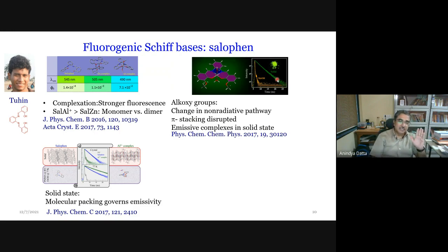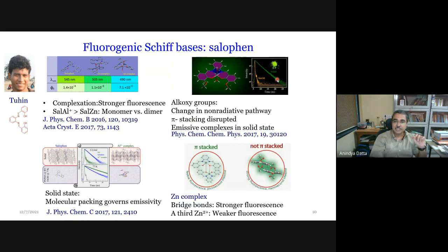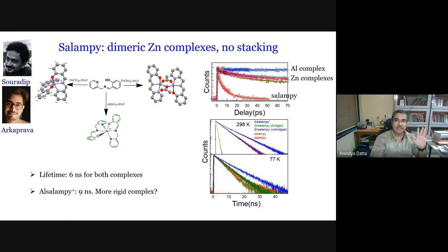So then we were left with this question: is it possible that zinc in these cases always forms a dimeric complex of some kind or the other? So then we thought, is it possible to make zinc complexes that are strongly fluorescent? The challenge was to find zinc complexes that are not pi stacked. And that is where my student Souradip came in, and this work is being carried forward by Arkaprava. Souradip found out from literature that Salampy, another Schiff base, was reported to form zinc complexes like this, or the report was monomer, but this is what we got, depending on which anion one used. So both the zinc complexes are such that in one unit you have two Salampy molecules, but they are not stacked. They are either side by side or perpendicular to each other.